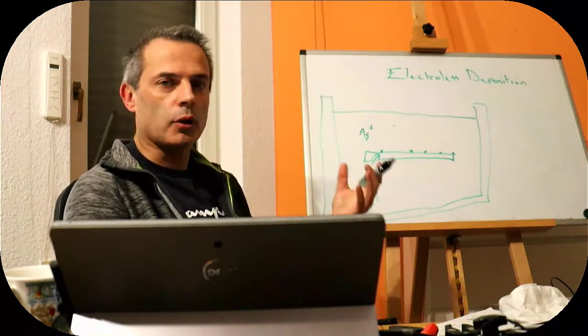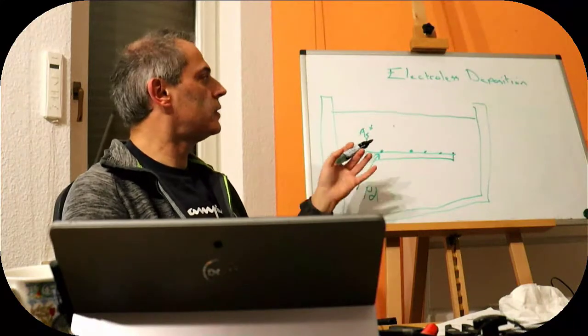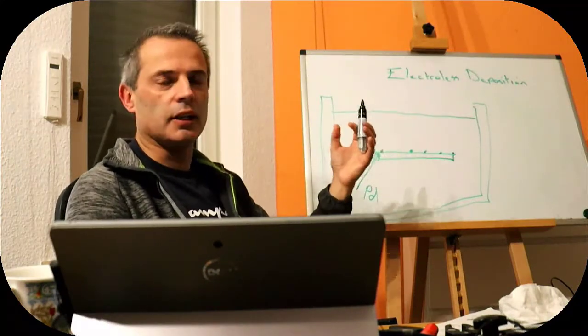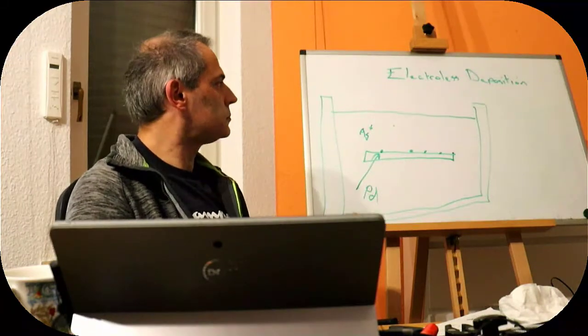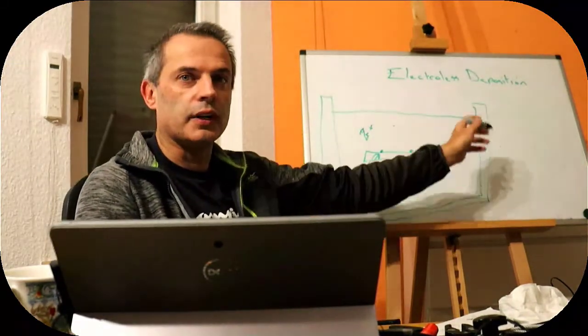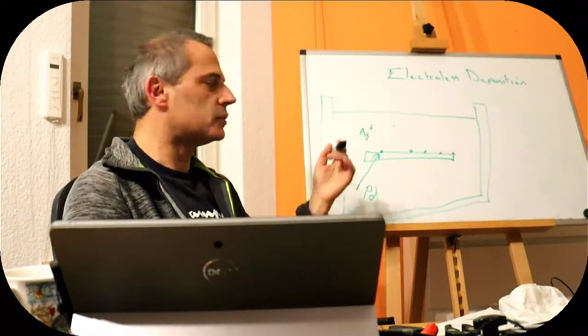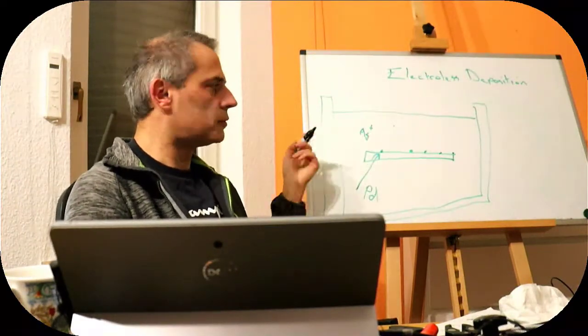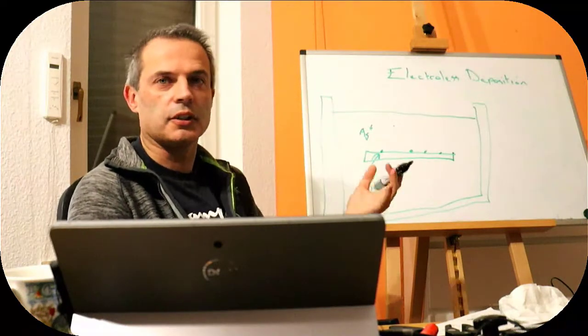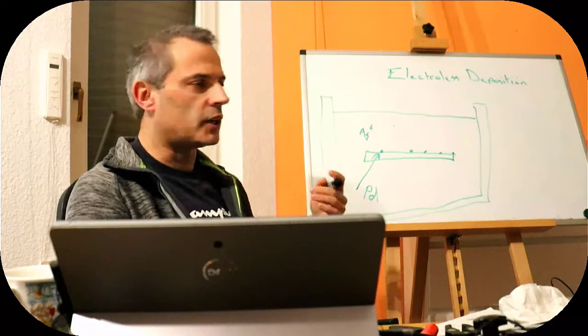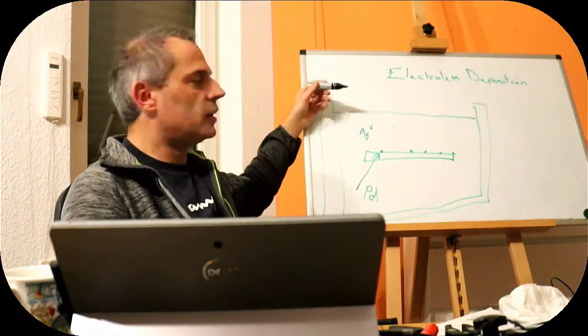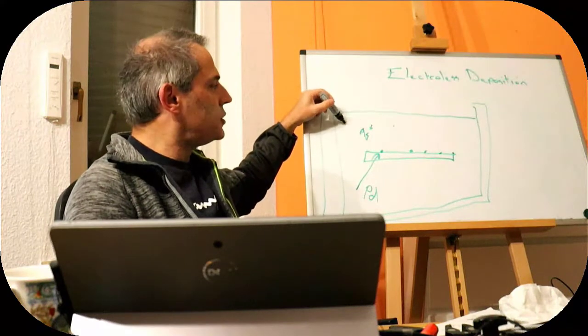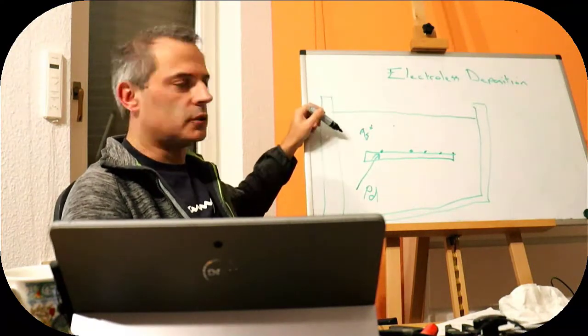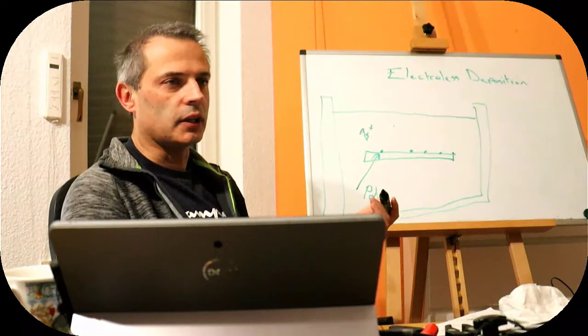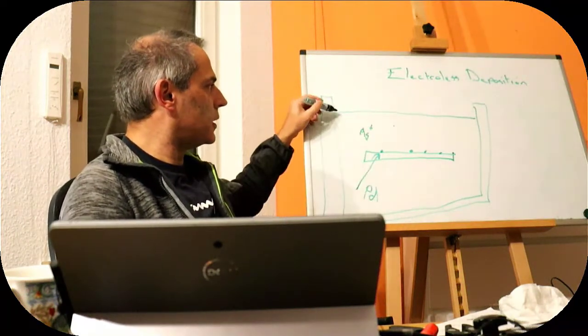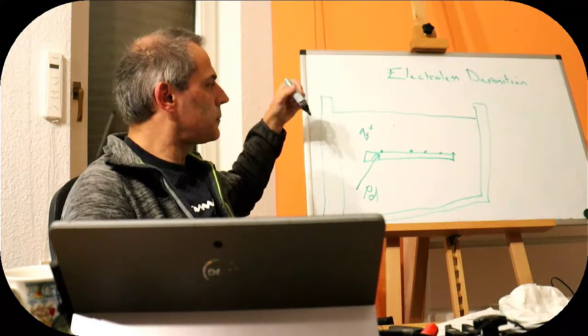Typically, whatever we do in a modern plating bath, they are stable enough that they will last for a reasonable amount of time, as long as there is no palladium in the solution. Likewise, we need to protect the walls of our container, because we don't want those to get covered with silver either. That will be expensive. We would lose the silver from our solution, and we would make everything dirty. We'd have to clean it. So to avoid that, there are other ions in there and other agents to ensure that we don't deposit so much on the walls. In this case, it's typically lead ions and complexing agents that stick to the surface.